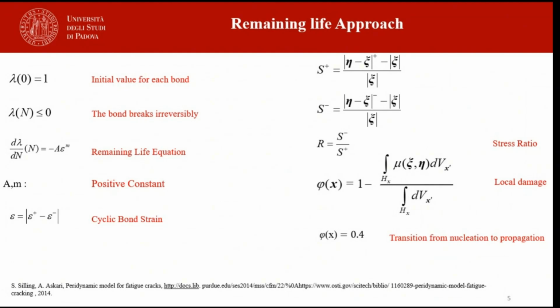Evolution of this parameter is described in the remaining life equation, where A and M are positive constants and epsilon is the cyclic bond strain. Stress ratio in peridynamics is defined as the minimum stress divided by the maximum stress, and local damage is the ratio of the number of broken bonds to the initial bonds. When this value equals 0.4, it marks the transition from nucleation to propagation.